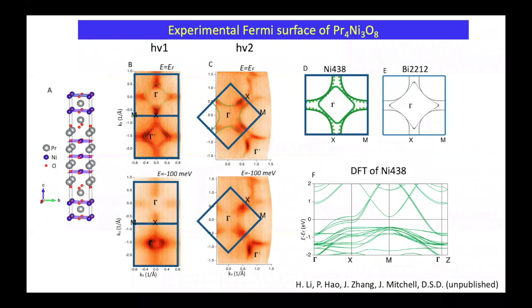Here's ARPES on it. These are Fermi surfaces and cuts slightly 100 meV below. We're using 2 photon energies to pick out various parts of the electronic structure. You can see sort of hole-like things here, electron-like things here. We put them all together, and this is what we get. And I'm comparing to an overdoped Bi2212 Fermi surface with bilayer splitting. Here there's trilayer splitting. So there's a dashed one here that's hard for us to explicitly resolve. And here's DFT of this, again, 1, 2, 3 of these bands, because it's a trilayer nickelate. And that's very similar to cuprates, if you like, nodal and antinodal states.